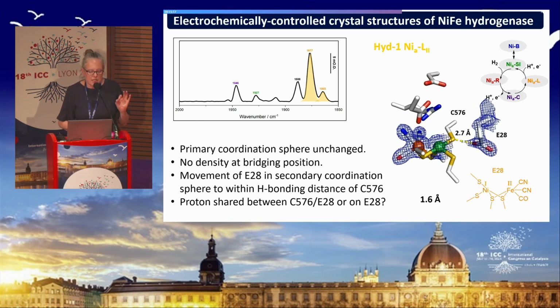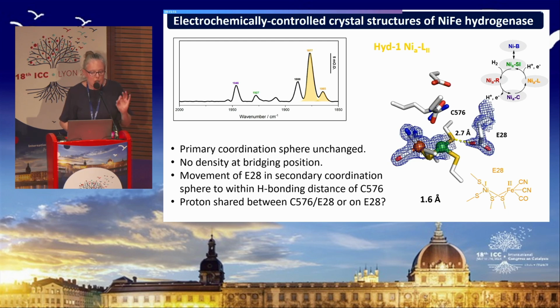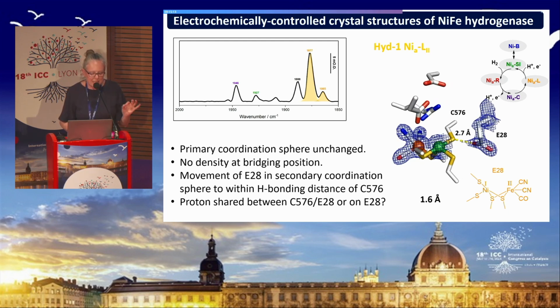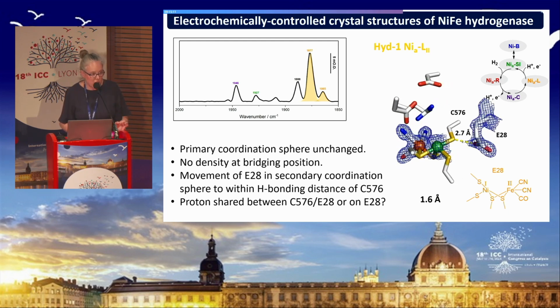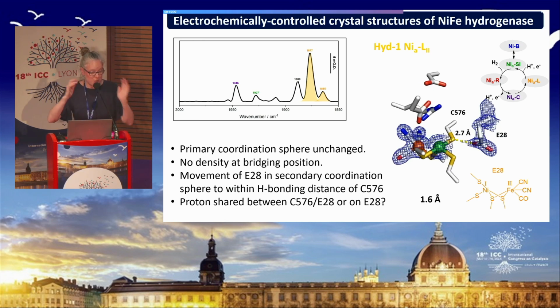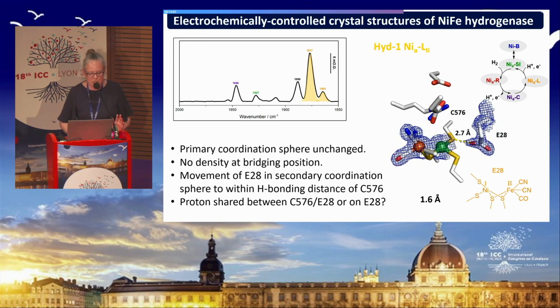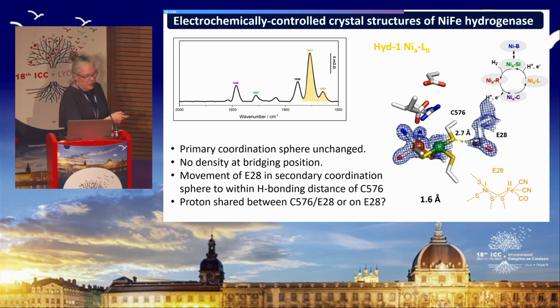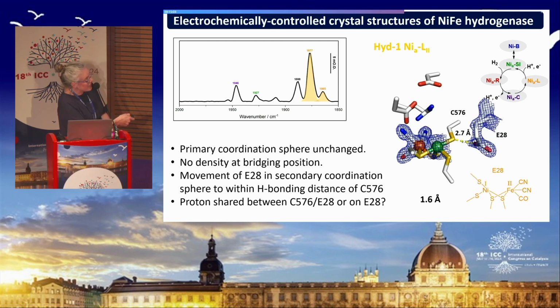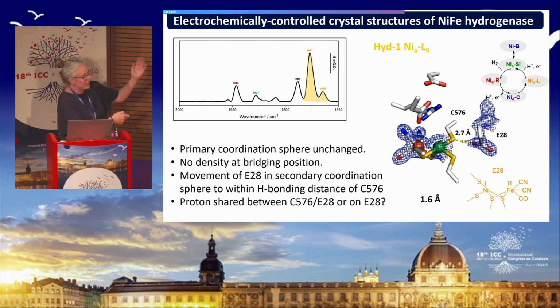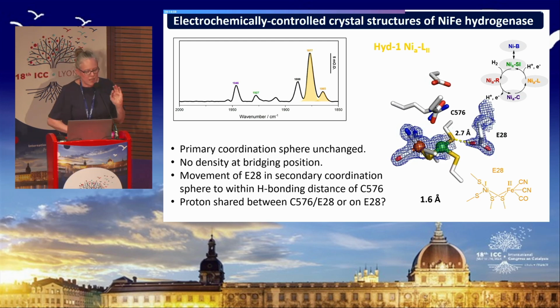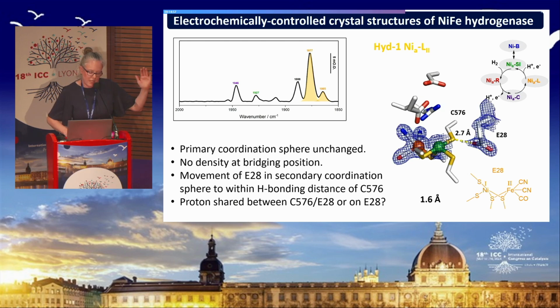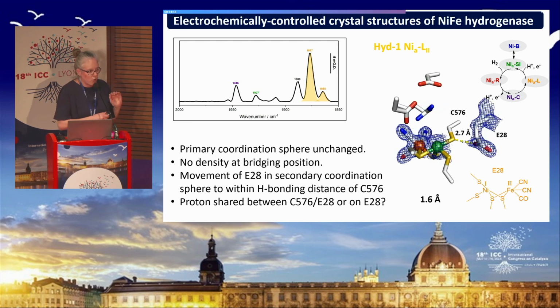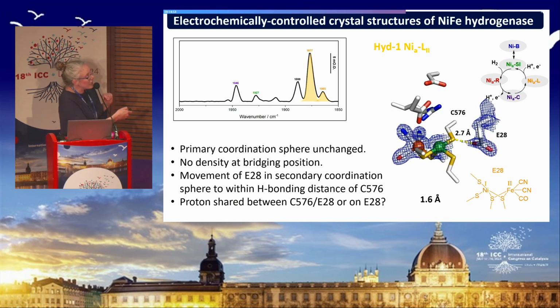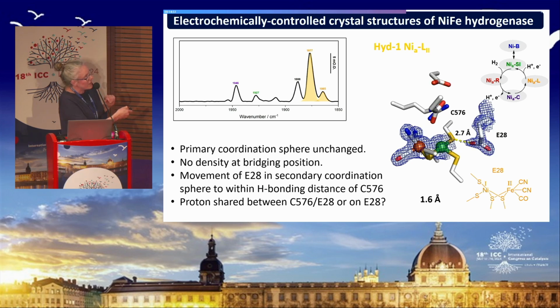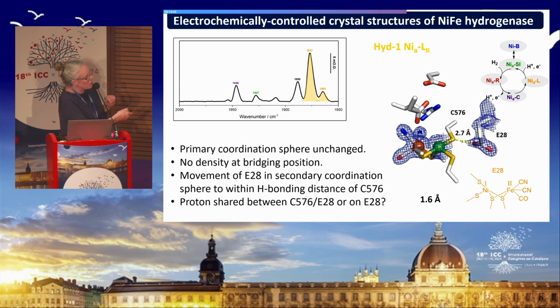And from the infrared spectra, we can see that this is a mixture of nickel-L2 with a little bit of nickel-L3 present. So we've now moved that proton a little bit further away from the active site. And the really important point here is that this glutamate side chain has now undergone a little flick to bring its position close enough for hydrogen bonding or tunneling of a proton directly from that cysteine residue to the glutamate.